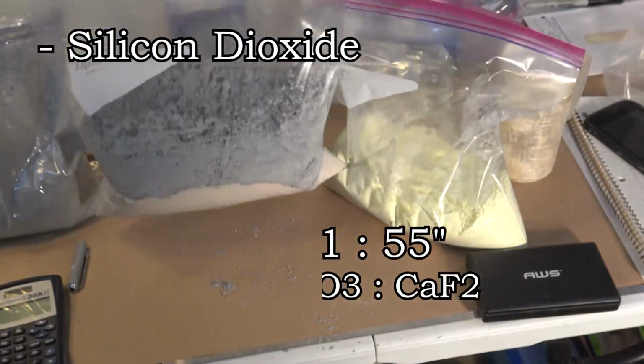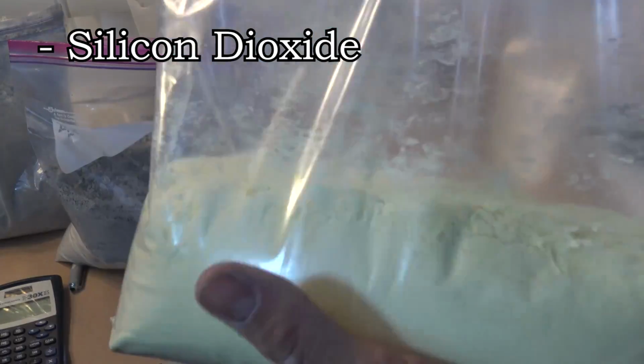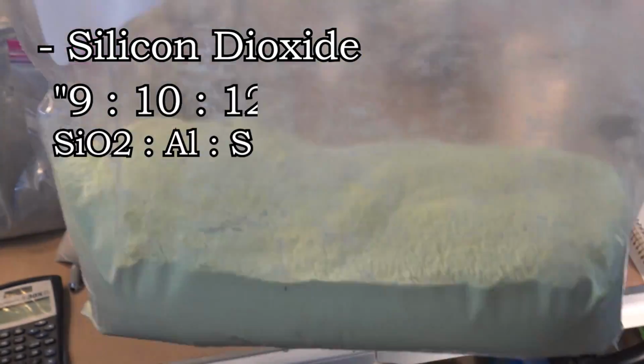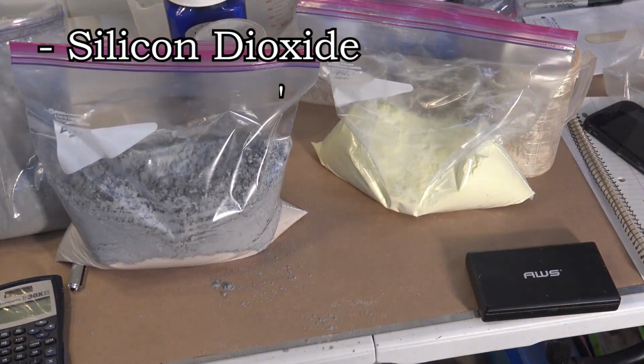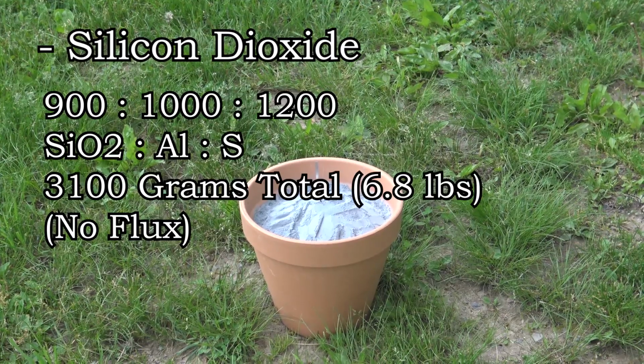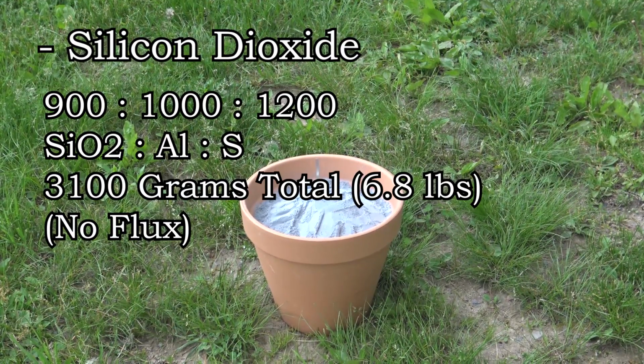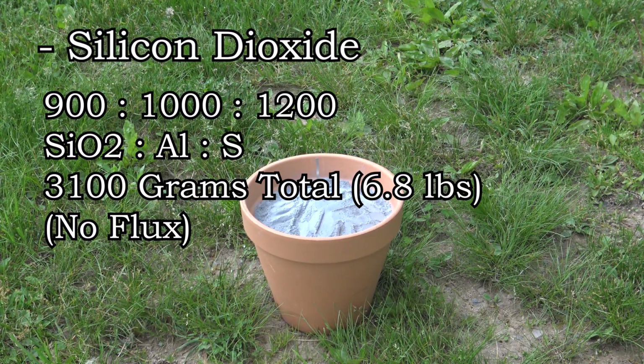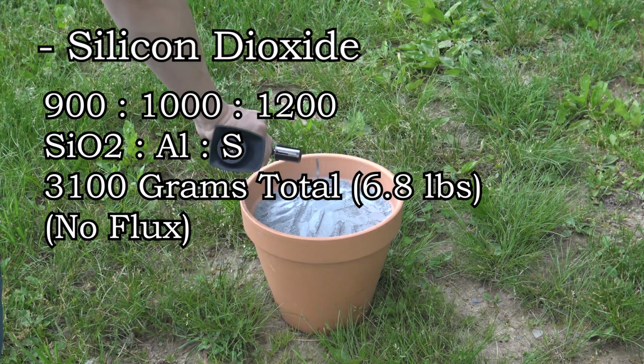one first. So for our first extraction, we're going to need silicon dioxide, aluminum, and sulfur in a 9 to 10 to 12 ratio. Starting with 900 grams of silica to make it easy, and working the rest out from there gets us our complete formula totaling 3,100 grams, or over 6 3/4 pounds.